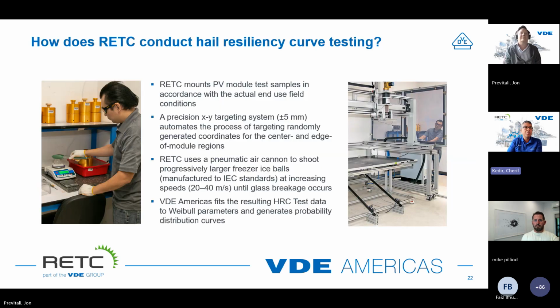We do that very simply. There's really no magic to it. We spent an inordinate amount of time figuring out how to make ice. It turns out to be very simple, but quite complicated to get there. So we make very clear ice. We reduce the inclusions to an absolute bare minimum. And the reason we do that is for one simple goal, and it is to make the impact as repeatable as possible. So that if we're trying to impact, say, 20 modules with a 2-inch ice ball, we want those repeated impacts to be as close to each other as possible, so that the kinetic energy that the module sees doesn't vary from impact to impact unless we want it to.